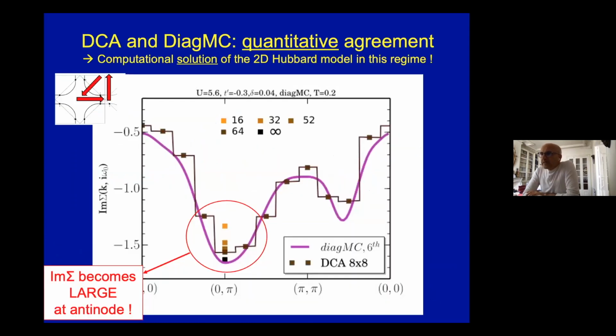In the specific case at hand, this curve, which actually in this form was never published anywhere, surprisingly, but is related to the article I just showed you, demonstrates that diagrammatic Monte Carlo on one side and DCA extrapolated to infinite cluster size can be really made to match one another. The purple curve is diagrammatic Monte Carlo. The various data points here are DCA, and you see that this is following the self-energy along these paths.